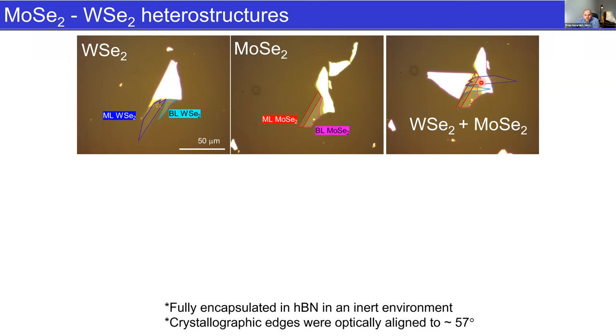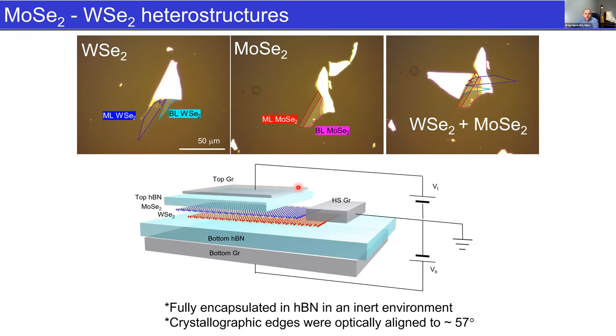And in here, you can see there's actually a bit of junk on top of the surface of the tungsten diselenide, and it happens to be little flakes of bilayer stuck on top, and you'll see that later as well. So that's what the active region of our heterostructure looks like, and then we fully encapsulate it in hexagonal boron nitride, and we add top and bottom graphene gates and a graphene gate that's in contact with the tungsten diselenide. So the nice thing is the hexagonal boron nitride is nearly identical thickness in both cases, so we can quite easily control independently the electric field, the vertical electric field in the device, or the doping, or we can apply a combination of the two.